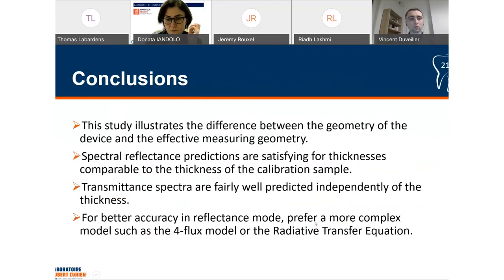To conclude, this study illustrates how important it is to take into account the effective measuring geometry, as it provides a huge increase in the prediction's accuracy. The spectral reflectances were predicted accurately only for the thicknesses close to the thickness of the calibration sample. So we would like to get rid of this thickness dependency.